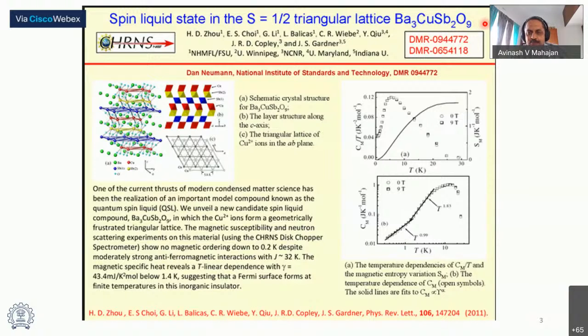So this is of the kind ABX3 three times. Many of the oxides of current interest have their origins in either a spinel lattice or a perovskite lattice and so forth. So this one really has an origin in the perovskite lattice. And the interest here was that, looking at copper, it's very much a triangular lattice that is present. And these people found a spin liquid state for this material. And so that got a lot of attention.